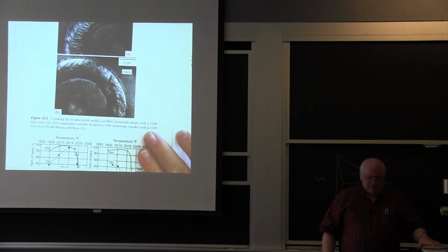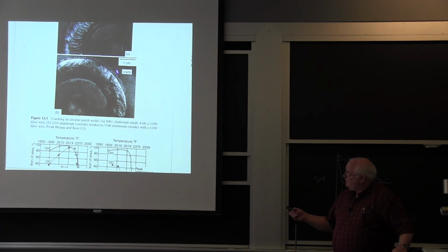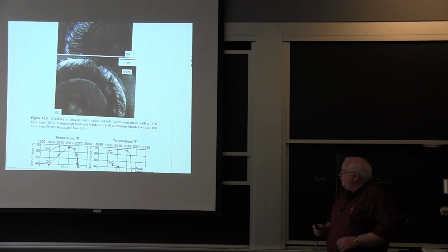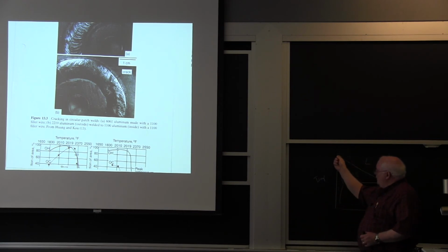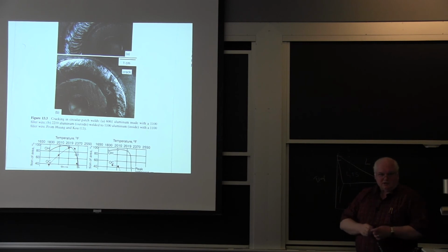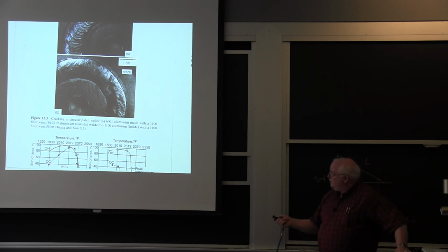This is an example of, actually that's hot tearing officially is the technical term. This is 2219 aluminum copper alloy on the outside, 1100 aluminum on the inside, 1100 filler metal. So I've got here at this interface where I have no crack, I have 1100 to 1100, I have a narrow freezing range, no cracks. Here I have 2219 and I have cracking all the way around. Just make a perfect cracking example.